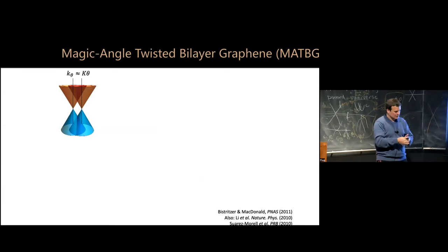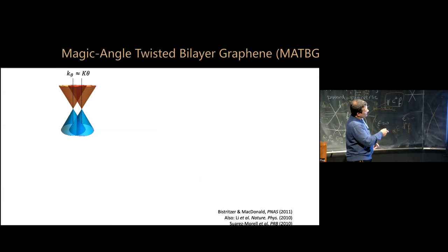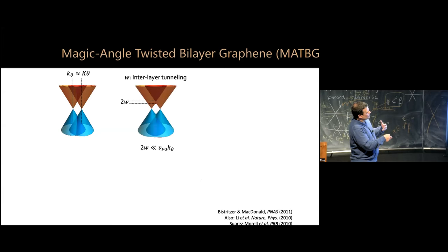And that tunneling hits the energy of that crossing point, okay? It leads to something we call band repulsion. It's like, you don't want these bumps to be together, okay? And there is a parameter which is called the interlayer tunneling, which governs that repulsion, okay? And these two cones are closer or further apart depending on the rotation angle in the two graphene sheets.